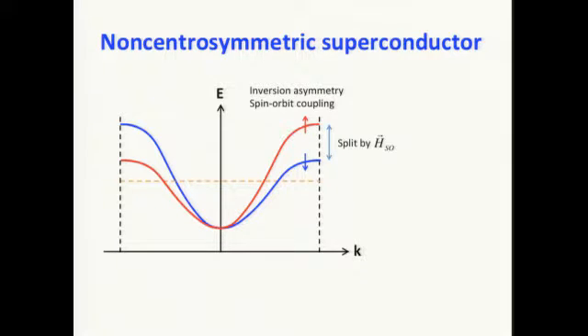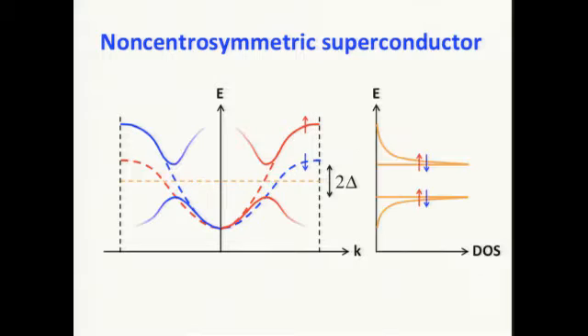And lastly, I just want to discuss briefly how we understand it. In a noncentrosymmetric metal with strong spin-orbit interaction, the spin-up and spin-down bands are split by the spin-orbit interaction, by an effective spin-orbit field, H_SO here. Electrons with opposite spin and opposite momentum can still pair up and form Cooper pairs, and you still have an energy gap like this, giving rise to two spikes in the density of states. The spin of these quasi-particle bands is locked to the out-of-plane direction by the spin-orbit interaction, so that when you apply an in-plane field, there's no Zeeman splitting that can be observed in this case.